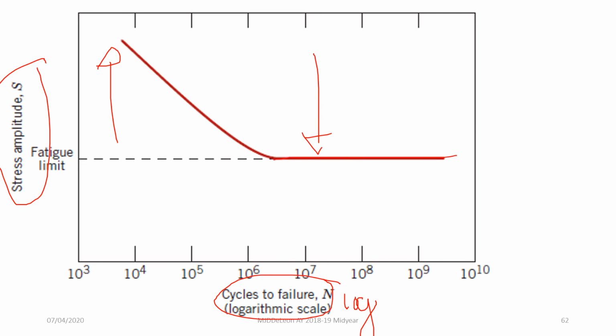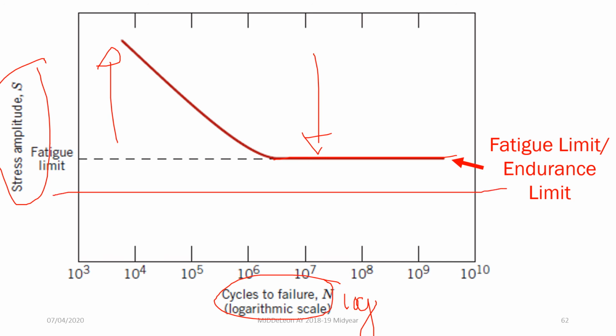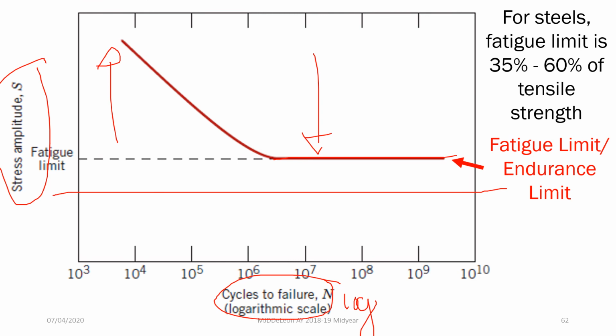In some materials, we have what we call your fatigue limit or endurance limit. So in this fatigue limit, if we apply stress lower than this fatigue limit, makita natin that your material would not fail under fatigue, will not experience fatigue if you apply that constant stress amplitude. So for steels, the fatigue limit is 35% to 60% of your tensile strength. So this fatigue limit or endurance limit phenomena is usually exhibited by our steels.